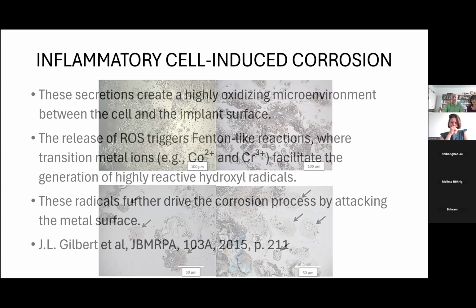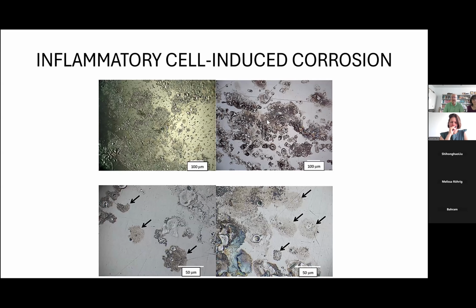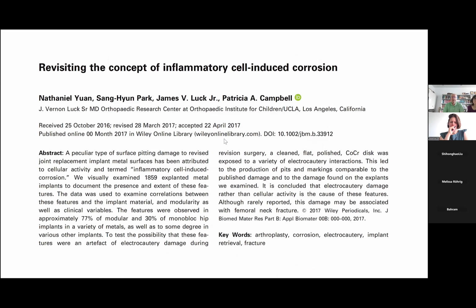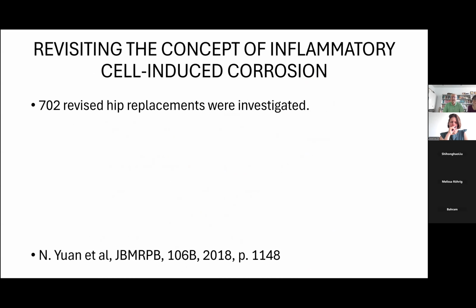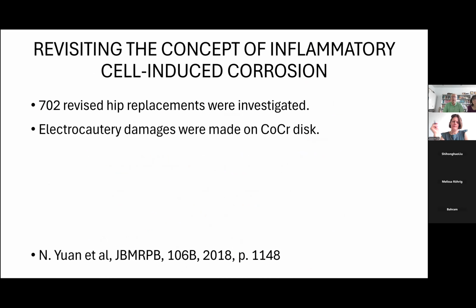And they give here some examples on retrievals. And they are saying that it is due to this cell-induced corrosion, it is what you have. I was very, very surprised. And a couple of years after, another paper was saying, okay, we need to revisit this concept. If you have a look at retrievals, with a large number, more than 700, they also took into account that the surgeon, in revision, uses electrocautery in order to cut the tissue or to coagulate the vessels. And of course, if you have a contact between the electrocautery device and the metal, you create sparks. And these sparks do create some damage on the metal.